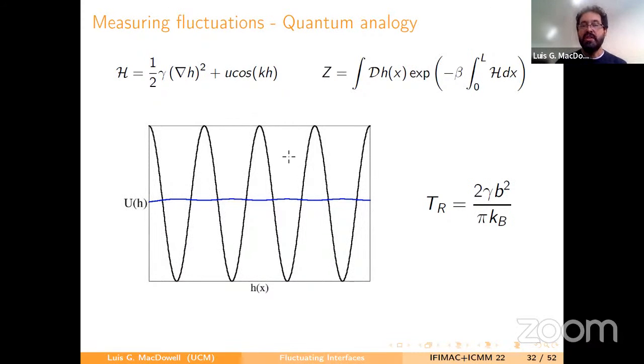And that occurs at the roughening temperature. Okay, what is going on at the roughening temperature? Well, at the roughening temperature, none of the surface positions are privileged. So then the solid can take whichever surface position, and then it's behaving just like a liquid, like a fluid interface. By the way, this roughening transition was anticipated intuitively by Nicolás Cabrera many years ago, before it was actually